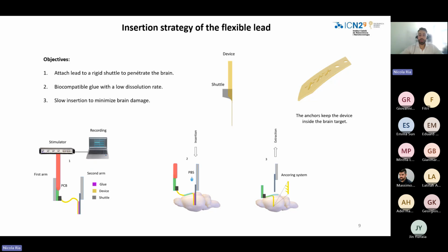So it was observed that usually during the extraction of the shuttle, the friction between the shuttle and the device was producing a displacement of the device. And to overcome this limitation, we designed an anchoring system made by flaps. And these flaps bend only when a force is applied to the device to pull it out from the brain. So in this way, the electrodes keep staying in place. And this is very important, in particular when it is necessary to target very small and deep brain nuclei.